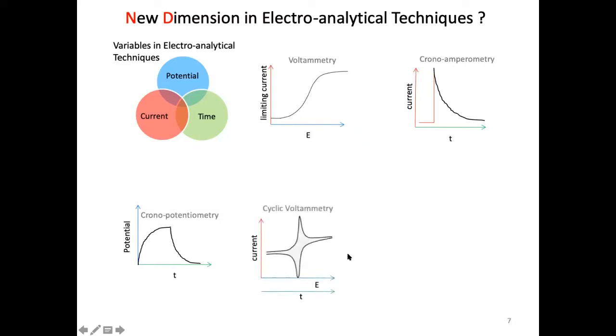Of course, we have cyclic voltammetry. The difference between voltammetry and cyclic voltammetry is that in voltammetry, we measure the steady state. We apply the potential, wait for some time, and sample the current. In the case of cyclic voltammetry, we measure current in real time. So the x-axis is not only potential but also time, because if you change the scan rate, the profile will change in cyclic voltammetry. So it is not only a technique where you are measuring current as a function of potential, but also as a function of time, and that is the difference between voltammetry and cyclic voltammetry.